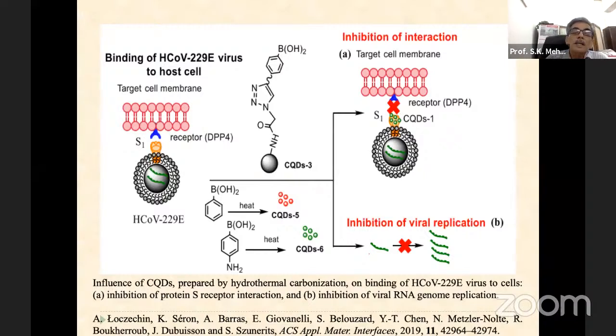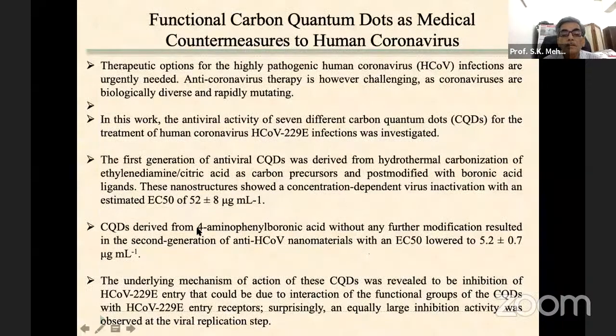So this study which was done was very interesting. Basically the idea was to make this receptor inactive. Once we make this inactive, naturally it will not penetrate into the cell membrane, and we are safe. There is no problem. And how to make this non-active? This was done by using quantum dots, nanoparticles. And here they used functionalized quantum dots, and these functionalized quantum dots were basically derived from 4-amino-phenyl boronic acid.